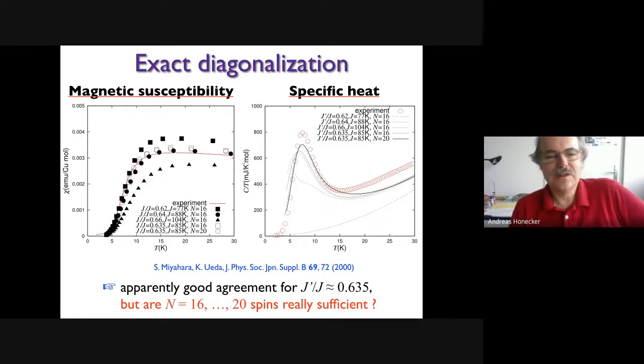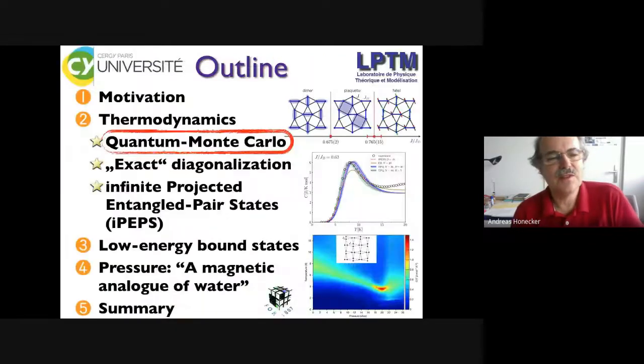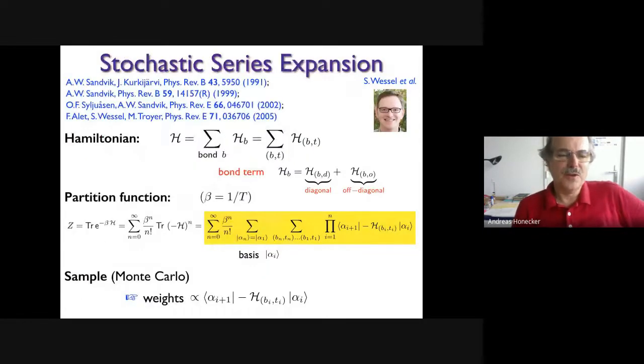But now if you compare at least these data sets, well, I'm not that sure about the comparison. And then if you think about it, that was done for 16 or 20 spins in 2 dimensions. 16 in 2 dimensions is 4 by 4. It's really a small system. And in fact, for the 16-site system, it's not only 4 by 4, it's also 2 to the 4. So the 16-site system doesn't really know whether it's 2 dimensions or 4 dimensions. So you might have reservations about the trustworthiness of these results. And so therefore, at least I wasn't happy with that particular computation. So the first thing that we did is actually doing quantum Monte Carlo.